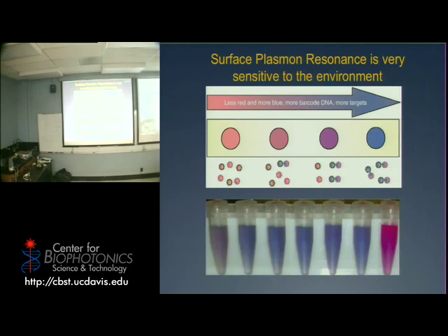The analogy is really not appropriate, but think in terms of a black hole, where you have all this mass centered in a very small volume. So with the 20 nanometers, it takes just a drop of an electrolyte to shield these electrostatic interactions. With the 5 nanometers, because of the size, and because it's a surface, so it scales with the power of 2, you have a much more intense electrostatic field. You need much more than 100 millimolar sodium chloride to shield that effect. Make sense? Yes?